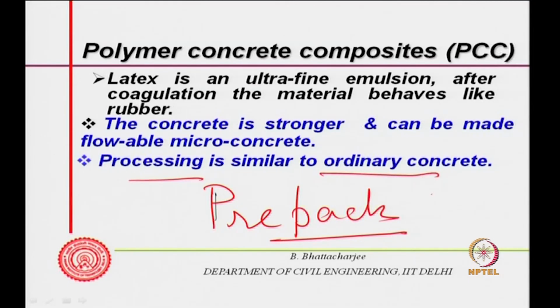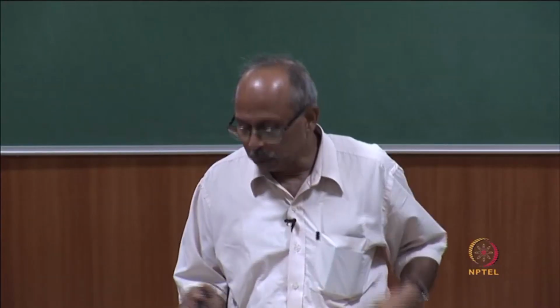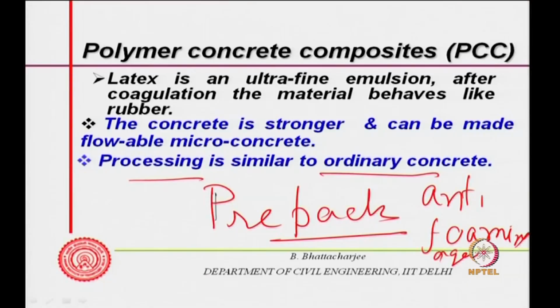But if you are making it yourself, then the processing is almost similar, but you must have some kind of anti-foaming agent, because these very fine spherical particles tend to generate a lot of foam. So, you must have an anti-foaming agent. Some plasticizers and other admixtures could be there, but an anti-foaming agent is very much required.